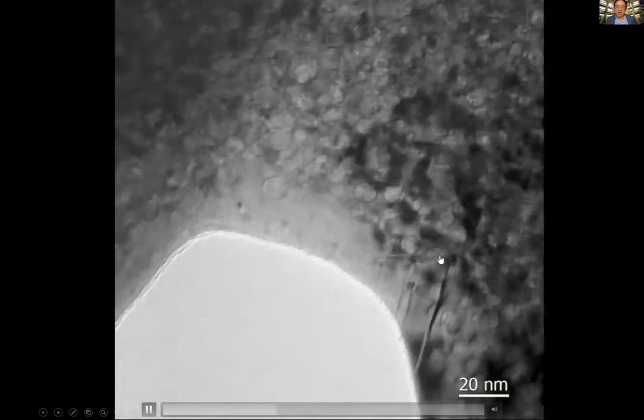So we made a notch, and when we deform it, you can see these partial dislocations and stacking faults. Without the helium, they would just move very, very far. But with the helium, they get stopped at the helium bubbles, so they don't go very far. These are almost like precipitates that stop the dislocation avalanche.